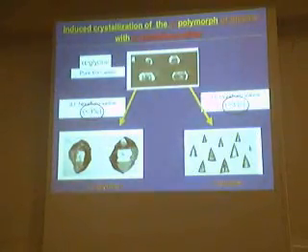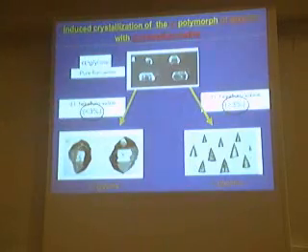So now what we're saying here is, from a very empirical study, if you like, that at the onset of crystallization the structure of the nucleus is very similar to that of the mature crystal, and by going to the morphology and the structure of the mature polymorph, we can design a molecule which can be used to perturb the nucleation of the more stable polymorph and to go to another polymorph of the system. Okay? It's crystal engineering, morphology engineering and crystal engineering. The original definition. Yeah. The original definition.